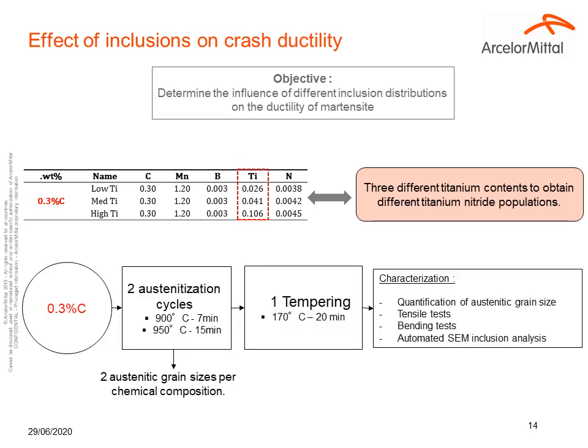We realized on each steel 2 austenitization cycles between 900 and 950 degrees Celsius to obtain 2 austenite grain sizes per chemical composition, and just one tempering temperature, which is 170 degrees Celsius. The characterization was carried out on prior austenite grain size, then on tensile test and bending test, and also an automated inclusion analysis has been done.